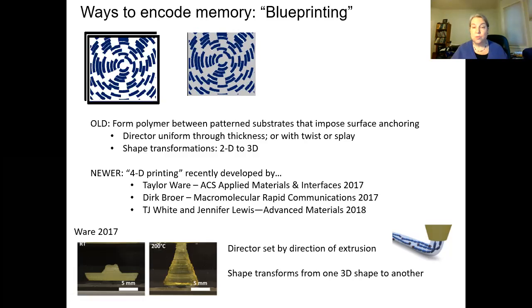You can also put some twist in it, so that instead of patterning the two pieces of glass at the same time, you can pattern one piece of glass with the pattern and the one behind it with, say, a 90-degree twist. And if you dope the liquid crystal with just a little bit of chiral dopant, which breaks the symmetry between rotating clockwise or counterclockwise between the two substrates, you can actually get some of those twisted structures. But whatever this is, it's essentially a very thin two-dimensional object that's flat and as polymerized. And then when you heat it, it could transform into any kind of 3D shape. So that was the very first method that was used for patterning these things.